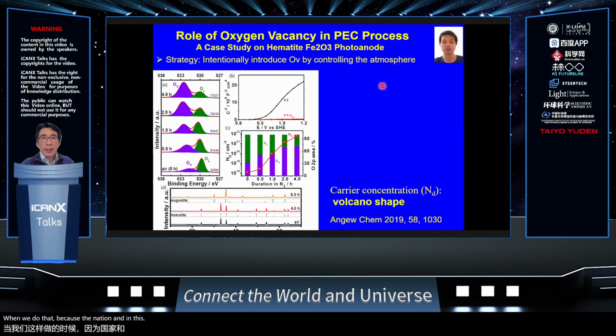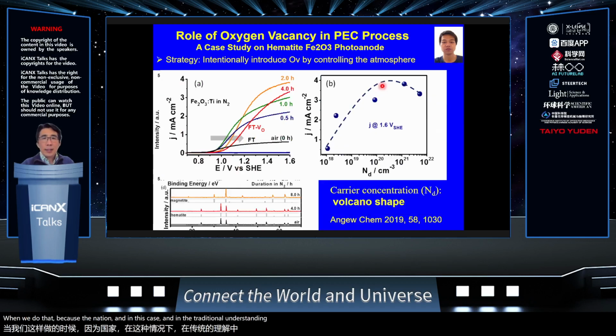And in this case, the traditional understanding is that if you increase the oxygen vacancy, it will increase the bulk transportation, and in some way it's correct. If we look at the film we prepared in air and in nitrogen for different times, we will see the photocurrent increased after we introduced the oxygen vacancy in nitrogen, but it's not a linear increase.